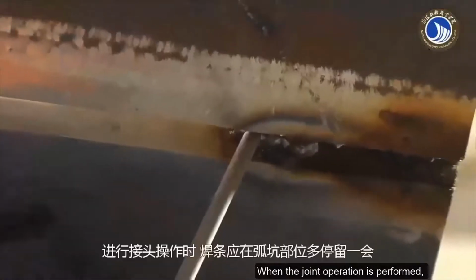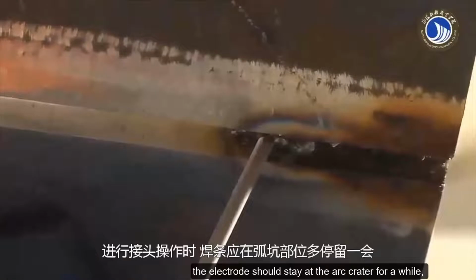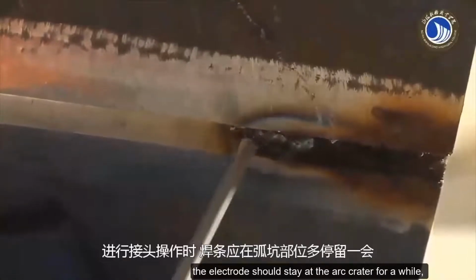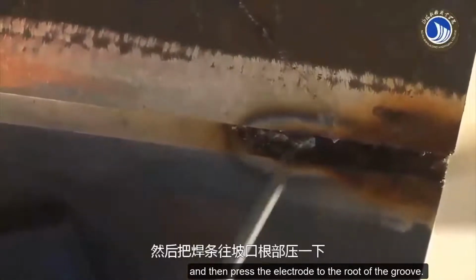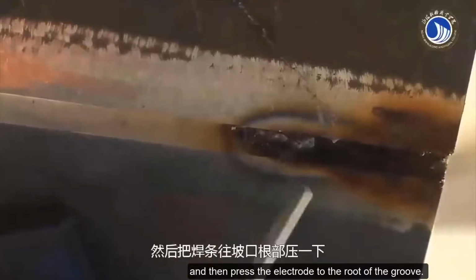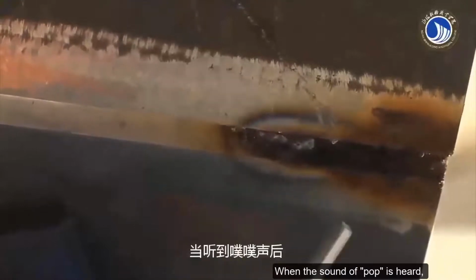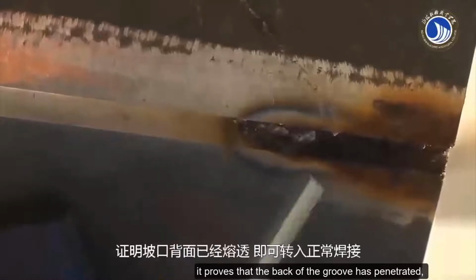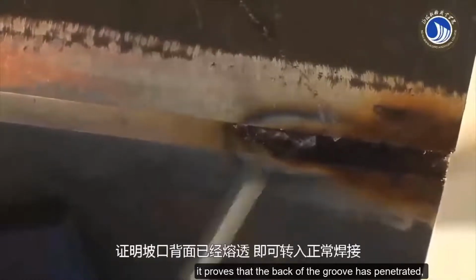When the joint operation is performed, the electrode should stay at the arc crater for a while, and then press the electrode to the root of the groove. When the sound of a pop is heard, it proves that the back of the groove has been penetrated, and you can transfer to normal welding.